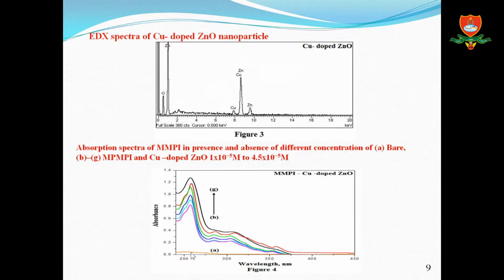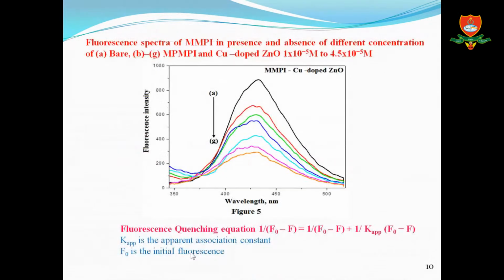Then, the absorption and emission spectrum of MMPI. It indicates the nanocrystals do not adjust to the excitations of the ligand. At 257 nanometer is due to the absorptions of the MMPI. The effect of increasing concentrations of nanoparticle on the emission spectra, the apparent association constants have been calculated using fluorescence quenching equations.